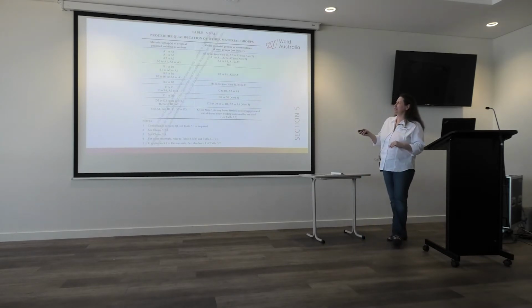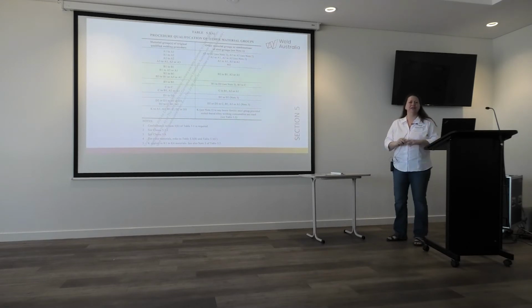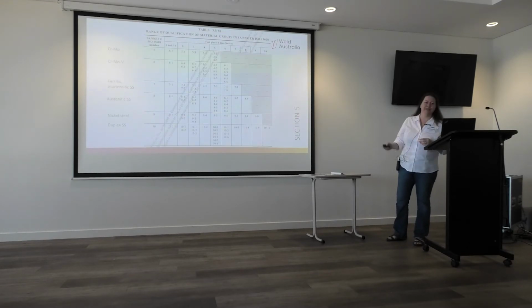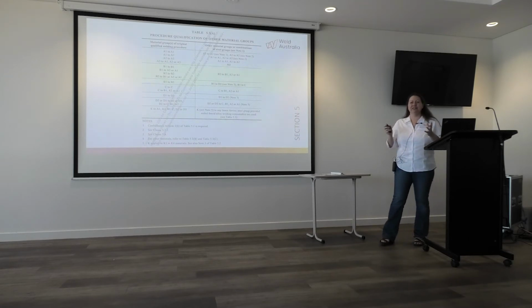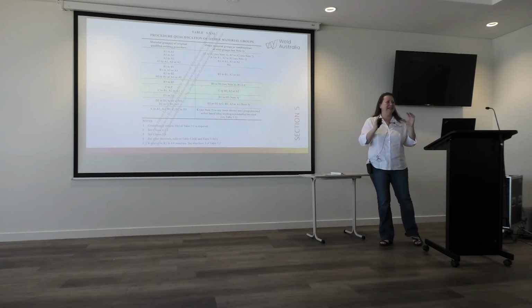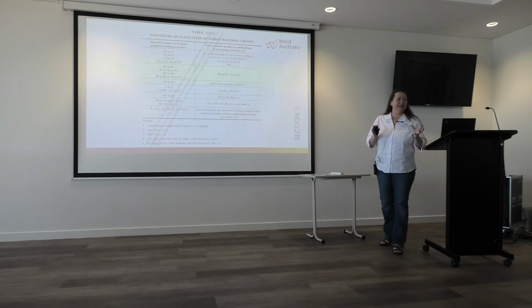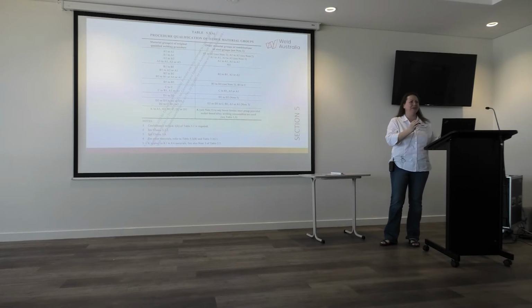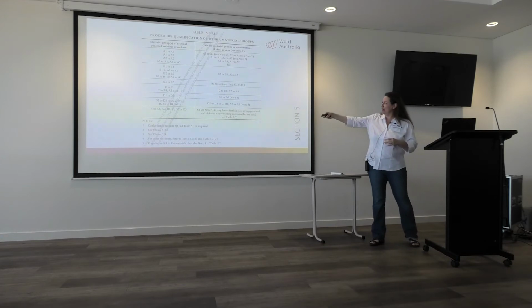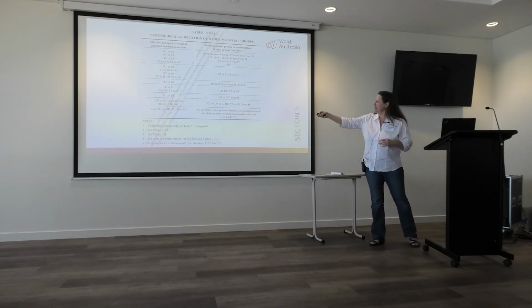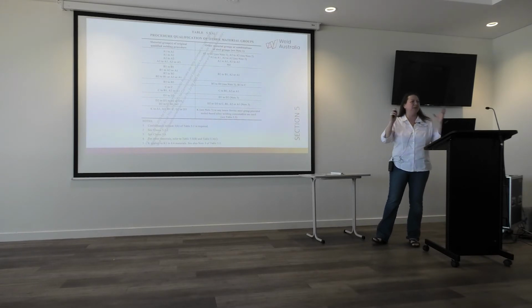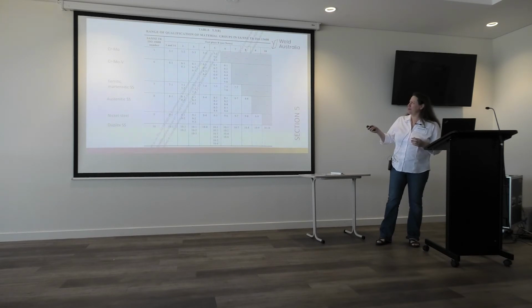So this is the procedure qualification table that we know and love. I tried to update this to what we wanted with the ISO. But with our way of classification, because our classification, as I said, is a bit eclectic, it sort of grew organically over time, and it wasn't updated the way that ISO was. We kept this, but also added in the B1, and so added B5. So just added in the ones that changed, but kept the format of the table exactly the same. And instead added this table 5.3b.